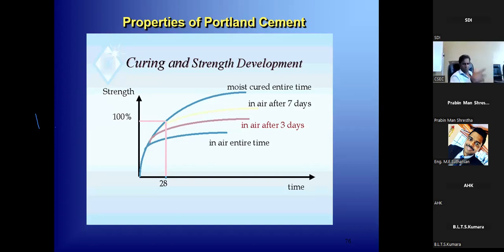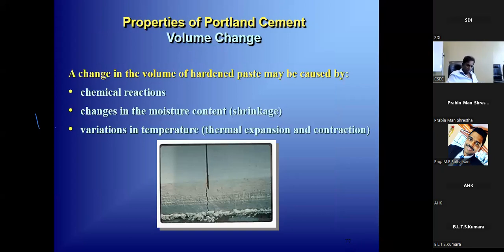And curing concrete, I can talk for hours, but what is basic is to put enough water for the hydration reaction to continue. So different methods. Try to reduce the escape of water. You can even use curing compounds so that you trap the water inside and provide enough water within the concrete for the reaction to continue. That's what we are doing. Sometimes we put some polythene bags on top, right? To really prevent the water escaping. Sometimes we put some water ponding. We put a pond of water for that. So curing is quite important. Just remember that by doing these things, we can get good concrete. So that's to get the low carbon as well. So the volume change can happen with the cement. I'll skip that.